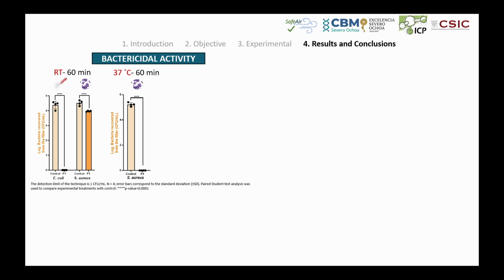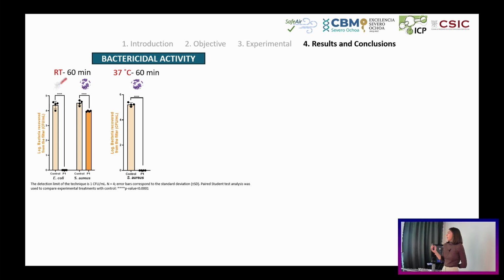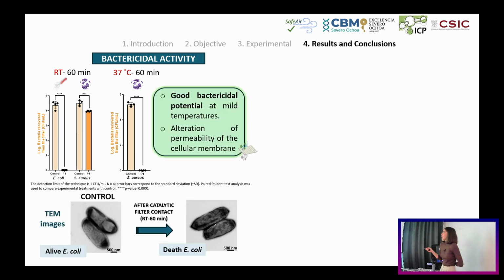Finally, the bactericidal activity was evaluated against Escherichia coli and Staphylococcus aureus, and we can see that at room temperature we inactivate Escherichia coli, but we need to increase this temperature until 37 degrees to inactivate the other bacteria. We see that after contact with the catalytic filter there is a higher dye penetration in the bacteria because of the change in the permeability of the cellular membrane.